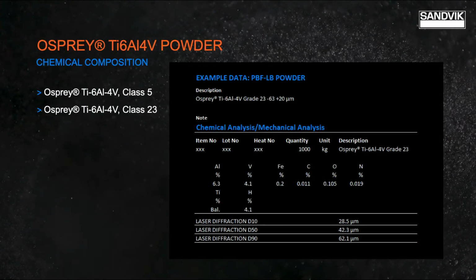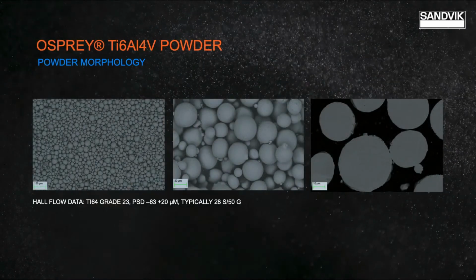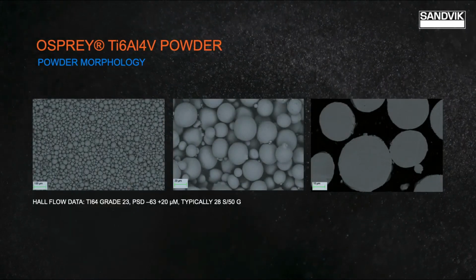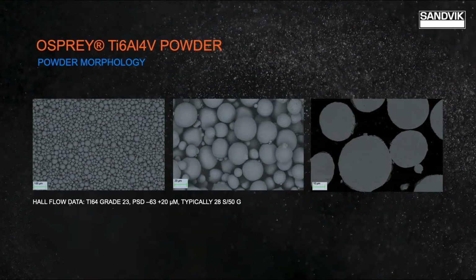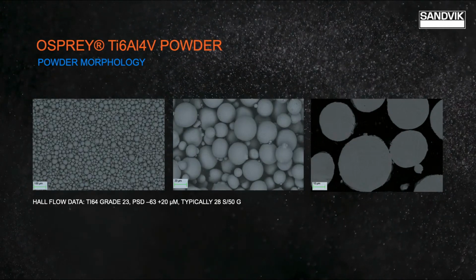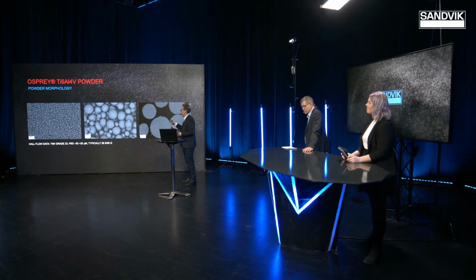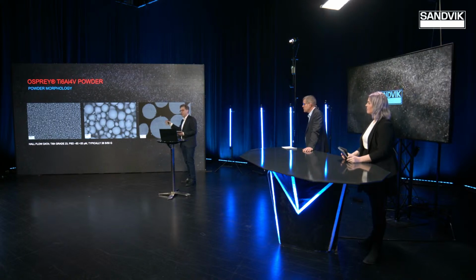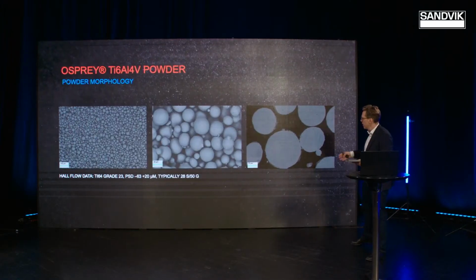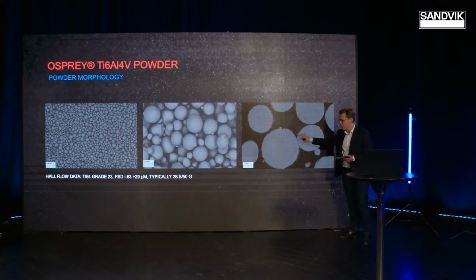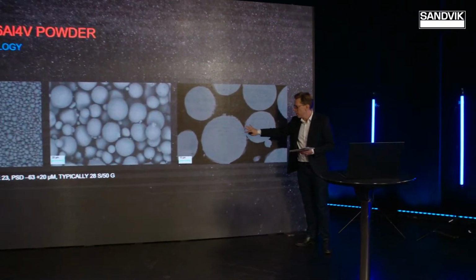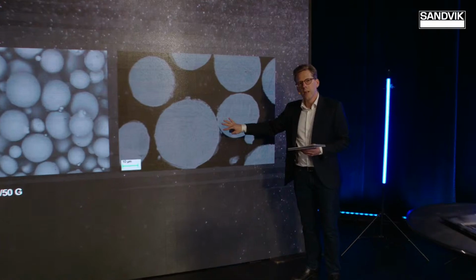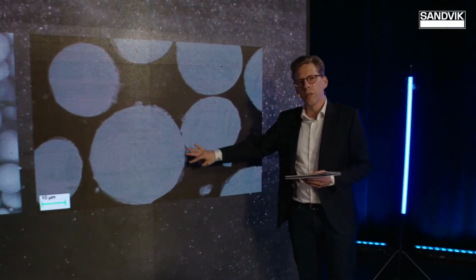Peter, what does the powder look like? Yes, and here you see typical micrographs of the powders. So one can say it's quite spherical, it flows quite well, and it is a good mix of the particle sizes that we want, in this case between 63 and 20 microns. As you can see to the right here is a cross-section of a powder particle that shows that it's fully alloyed. So it's the same alloy composition all through the powder particle.